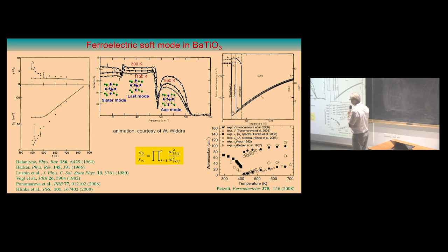And what is actually observed is that there is a phonon softening and splitting in ferroelectric phase transitions, but this is the soft lowest frequency phonon, and additionally a central mode is present. And it is another picture of the same. So here is some crossover between displacive and order disorder mechanism.